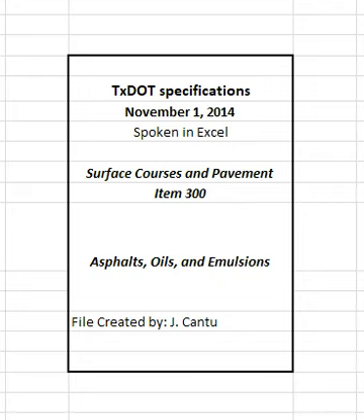Table 10. Polymer modified cationic emulsified asphalt. See table in specifications. 1. Exception to T59, bring the temperature on the lower thermometer slowly to 350 degrees Fahrenheit, plus or minus 10 degrees F. Maintain at this temperature for 20 minutes. Complete total distillation in 60 minutes, plus or minus 5 minutes, from the first application of heat. 2. CRS-2P must meet one of either the ductility or elastic recovery requirements.